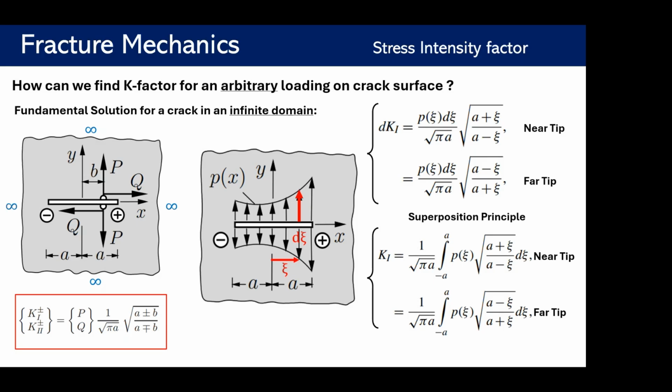So we have the fundamental solution. And as I said, if we have an arbitrary loading on the crack faces, I can use integration to find the stress intensity factor for any other problems.